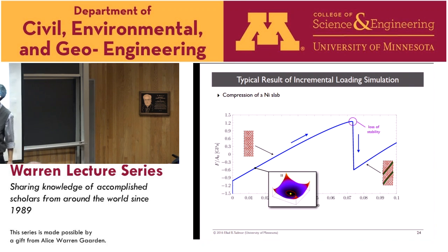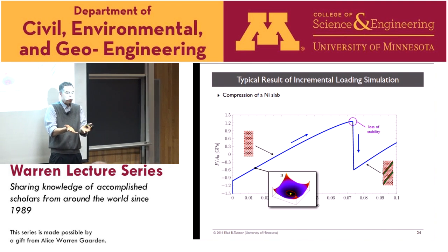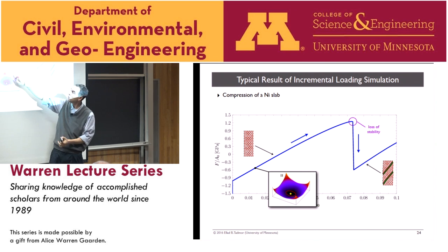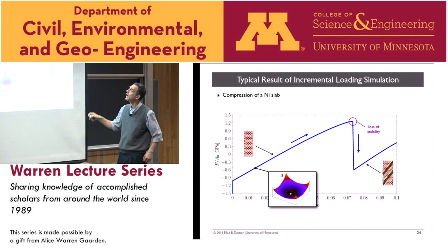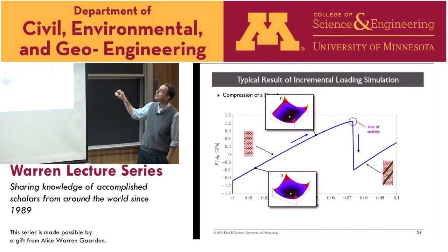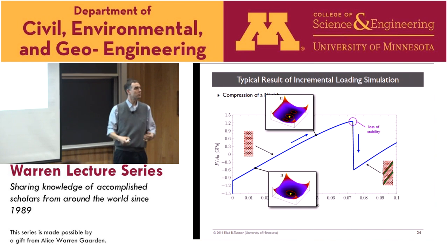And as you pull a little bit further, this surface changes, right? Because as lambda is changing, as you compress more, the shape of your energy surface is changing. So a little further higher up the curve, this minimum that you're in is still there. So the perfect state is still there. But look, you're getting additional states forming. Those are the defective states that are beginning to form. The one you're in is actually shrinking.